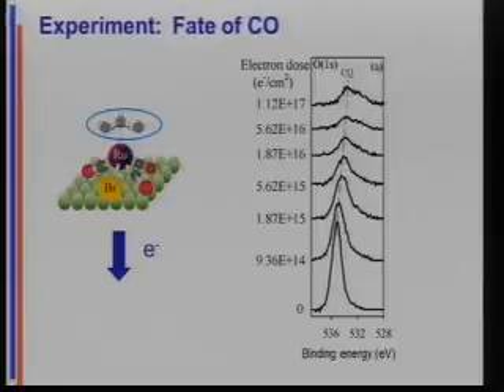Here's what happens when you do the experiment. So this is Howard's experiment, the surface science one. So it's on the substrate being irradiated. And what you can do is you can follow the oxygen in the XPS. So this is no electron flux here. Here's my carbonyls. And as you irradiate with electrons, you see the oxygen go away. Now, in this particular experiment, you can't figure out the carbon because they did it on a graphite substrate. We'll discuss that later, okay? But at least we're getting rid of the carbonyl oxygen.